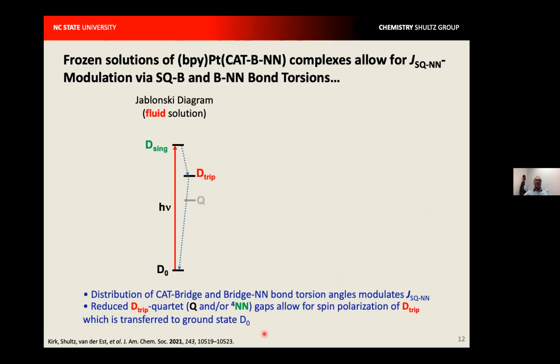The next thing that we wanted to look at, and it was predicted by our MCD studies, was that the excited states would have an amount of spin polarization to them. And after refining the model and doing some experiments, what we realized was we were doing these spin polarization experiments in frozen solutions. And so when you take a solution of these platinum complexes and you freeze them, you're getting a distribution of molecular conformations that can affect particularly the exchange coupling that results in an energy gap between D-trip and the quartet. And in particular, you're going to get some mole fraction of conformations where there is a very small energy gap between D-trip and the quartet state.